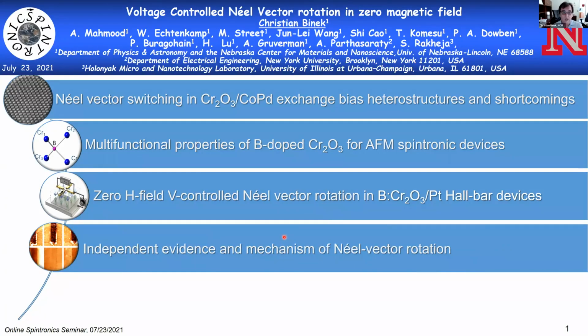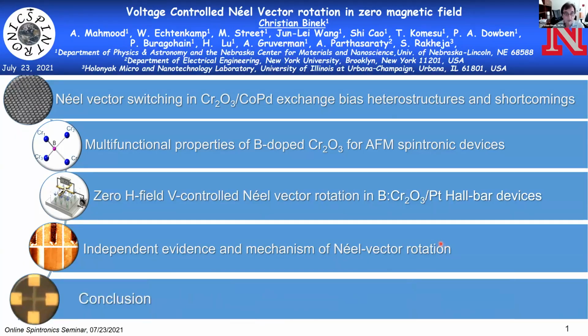I will then show that we also made a big effort to show that this switching effect we see in these devices, which is reflected in a change of the Hall resistance, is indeed a magnetic switching effect and not some other artifact. And for that, we teamed up with the group of Alexei Gruverman, and he, for example, did some atomic force microscopy imaging, and we had other independent measurements that show this effect is indeed magnetic in origin. And then finally, I will sum it up and conclude.